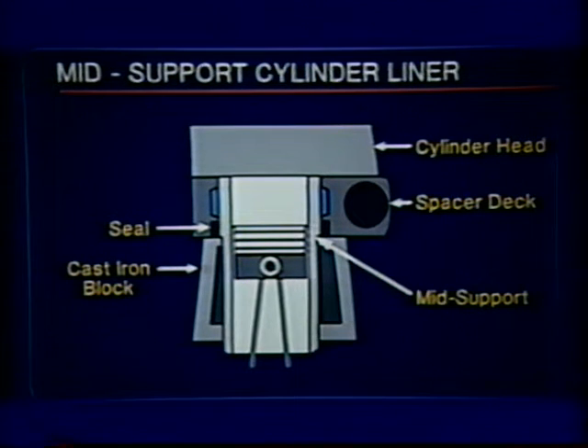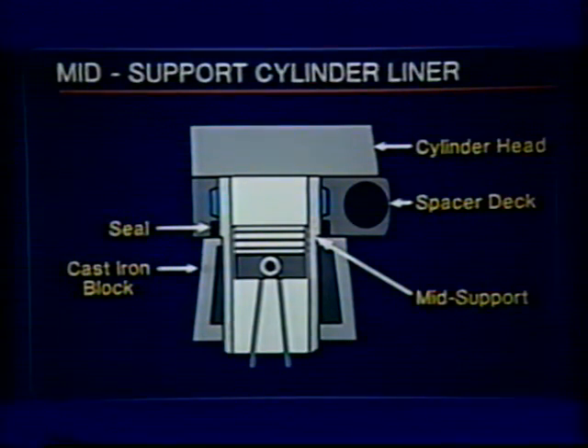The mid-support design allows for greater cooling around the very top of the liner, where the greatest amount of heat is generated. This allows the engine to use a high top ring piston design for low crevice volume. Coolant, supplied through an integrally cast manifold in the spacer deck, enters the spacer deck at each cylinder and flows around the liner and into the cylinder head. Since there is no top flange, the liner can be cooled almost to the cylinder head joint. This is important because of the high-mounted compression ring that gives the piston its low crevice volume, which is critical for emissions control and fuel efficiency.